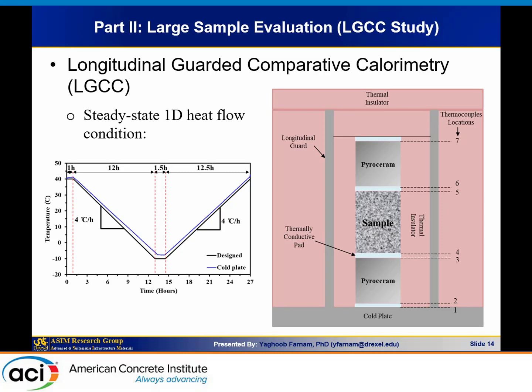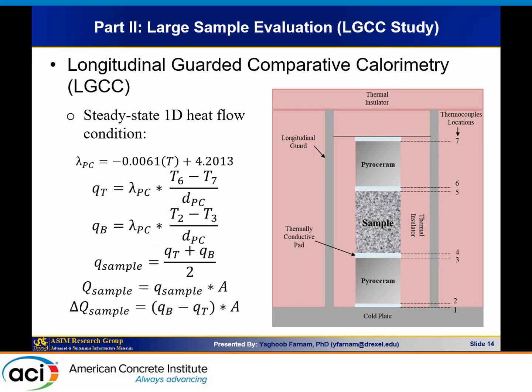We have some assumptions here. And the idea is that we have this cold plate. We could change the temperature. We put our sample, which is about 2 to 3 inches, inside. And then you do have thermocouples at the bottom and the top of the sample. And these are standard thermocouples. We use Pyroceram, a very expensive material. And we measure the temperature at different locations, 1, 2, 3, up to 7 different locations. And then it goes through some calculation. We could back calculate and find out the amount of heat flow as a function of temperature. But there are some assumptions here, some simplification, and we have to be very careful about that. But as we go slowly, we are very close to this steady state. So this could be a promising approach.